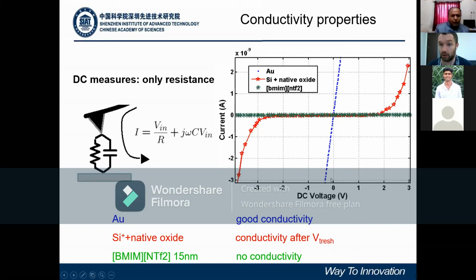Here there is an example: when the probe is in contact with a gold surface, there is an ohmic contact, while with a doped silicon with a native oxide, when the probe is in contact, there is conductivity only after reaching a threshold, so a sort of diode-like behavior. We also did some measurements on ionic liquids, solidified ionic liquids, and this is not conductive, so we have no conductivity.